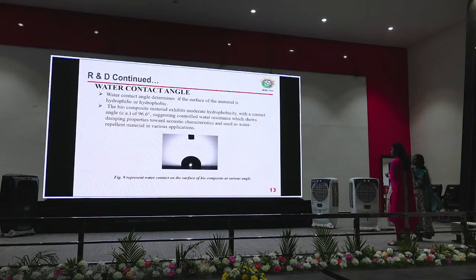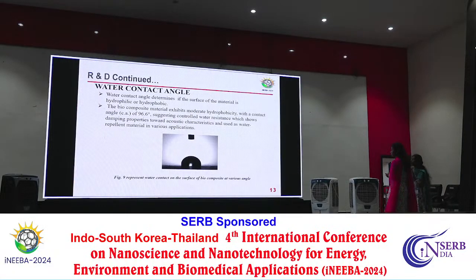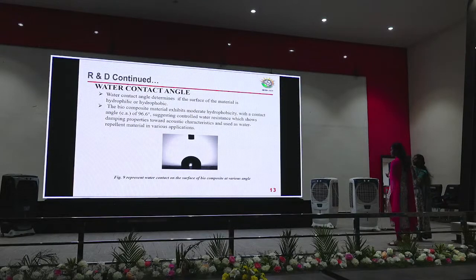Water contact angle is used to analyze how water droplets interact with our surface. In this result, we got a contact angle of 96.6 degrees. It shows hydrophobicity. If the contact angle is more than 90 degrees, the material has a hydrophobic nature. So our material can be further used as a water repellent material.